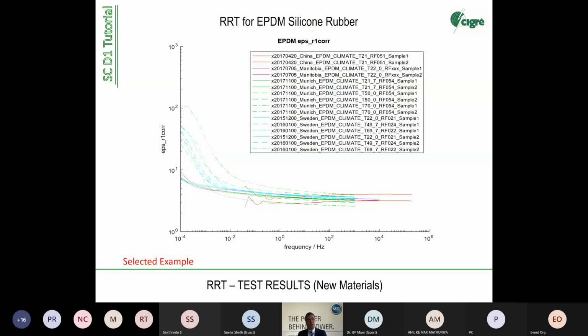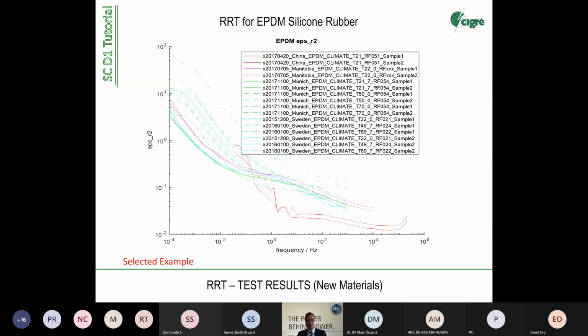Tracking and erosion performance is actually like extinguishing fire, extinguishing the arc. So you're using the same philosophy in order to get a good tracking and erosion resistance as making a material non-flammable. So that's clear, or at least for us it was clear, that we can have a real interpretation of the results. Also a very strong response here, a clear tendency.